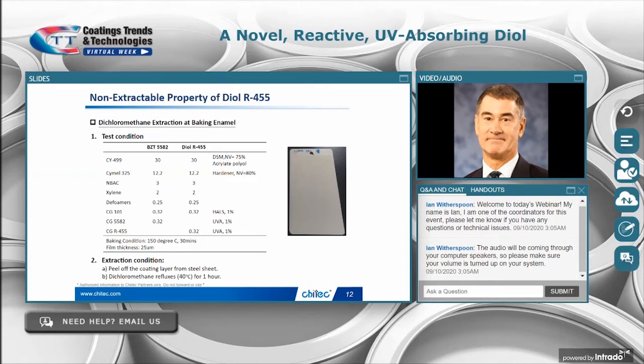And now on this slide, we are comparing R455 to a non-reactable benzotriazole, 5582. The R455 is expected to react with a melamine crosslinker. In this case, it's Cymel 325. And for the experiment, we chose methylene chloride as the UVA extraction solvent because it's a very aggressive solvent. It really swells the coating, and it should extract most things that are not cured into the film.